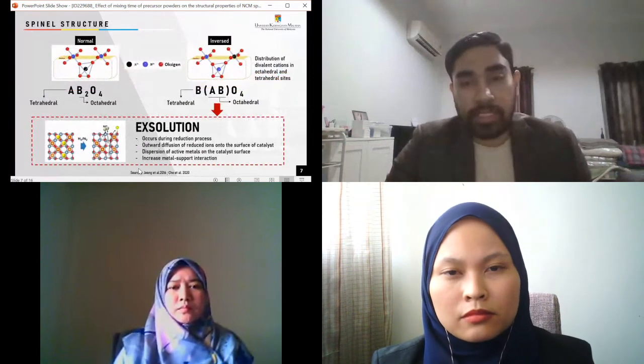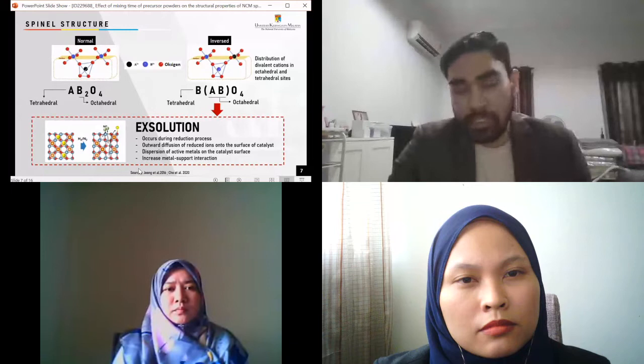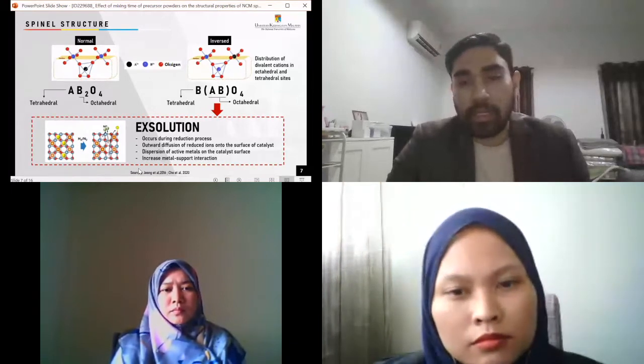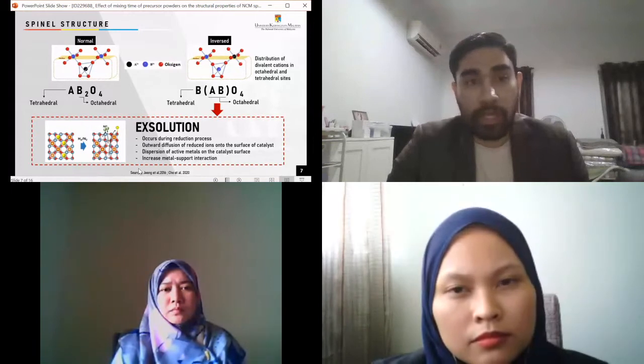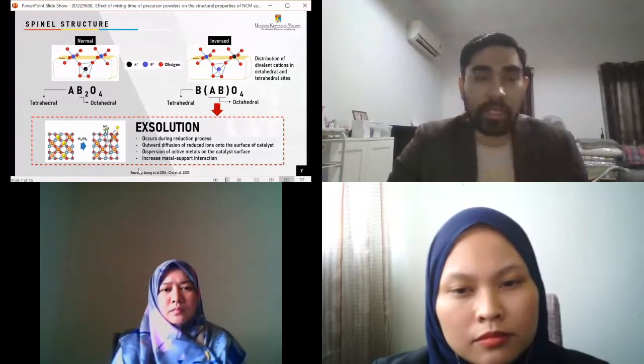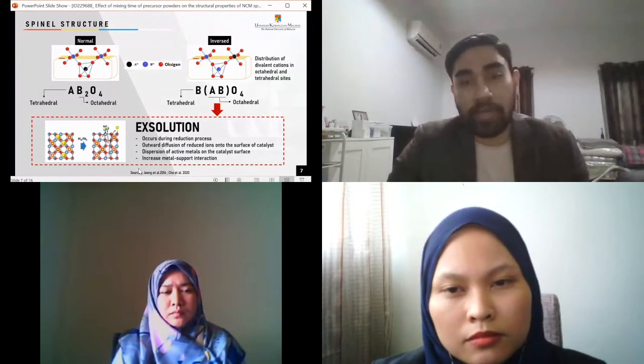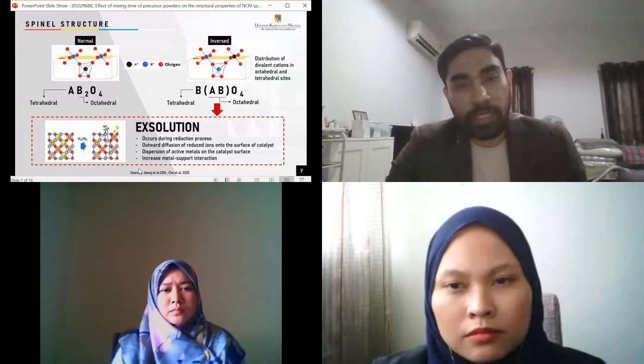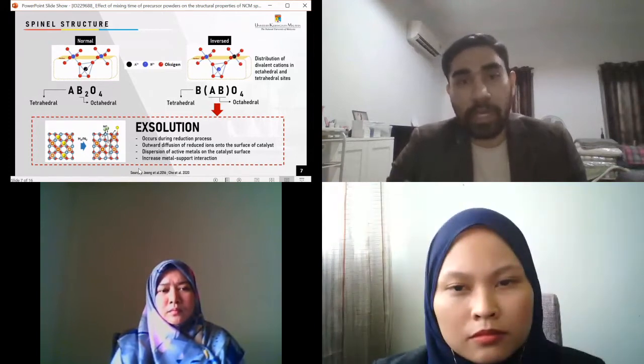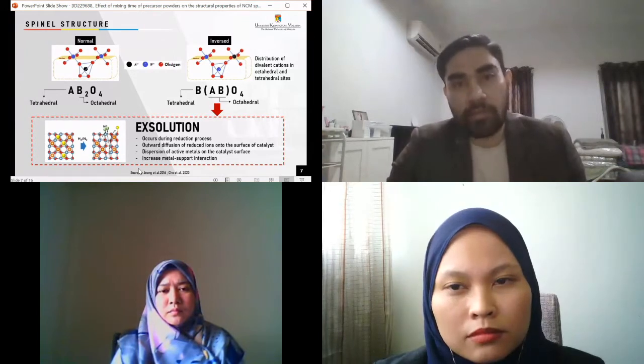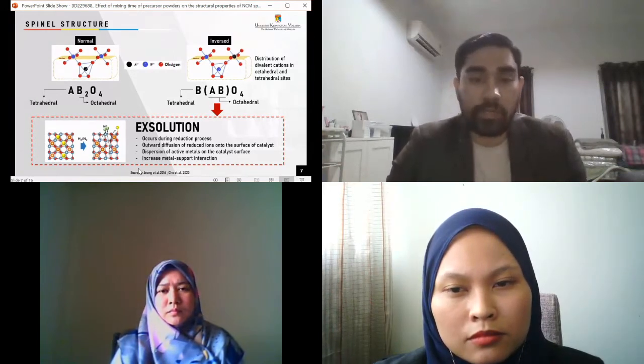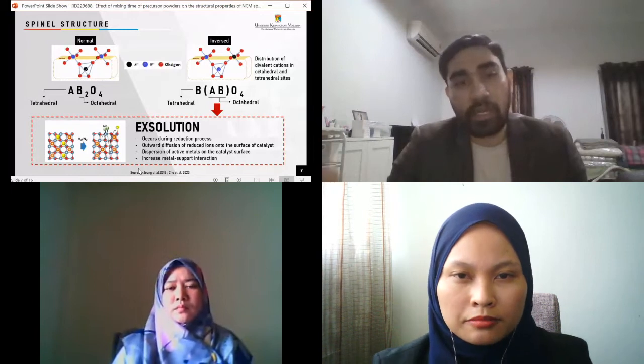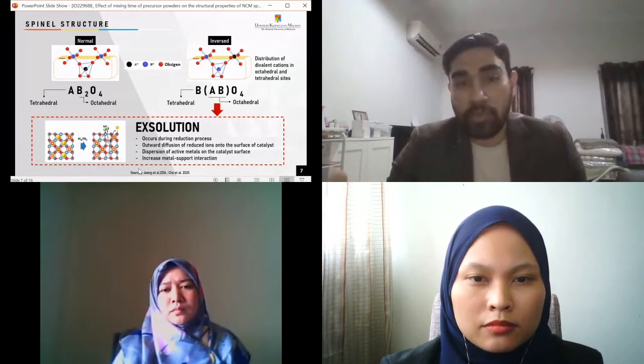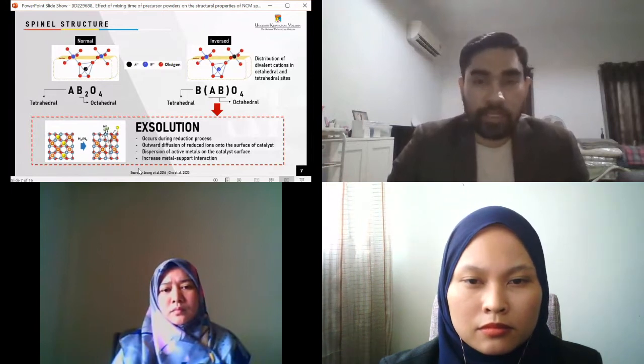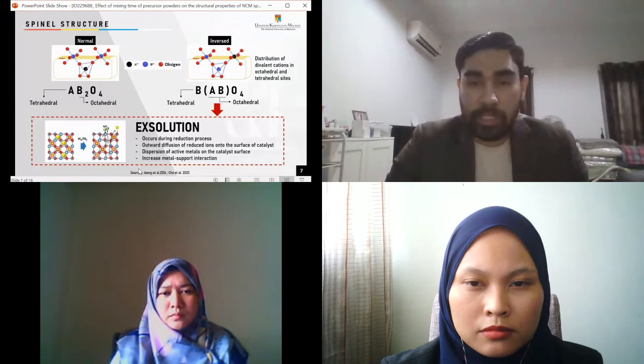When we consider spinel as a catalyst, we must also look into its structure. Normally, spinel is represented with a normal structure where the divalent ions reside in the tetrahedral sites. However, there is evidence showing that each spinel has a certain degree of inversion, where the spinel exists in an inverse form and the divalent ions, which are usually the active metal, reside in the octahedral sites. This allows the active metal to be exsoluted during the reduction process, especially in the anode environment, which is a reducing environment.